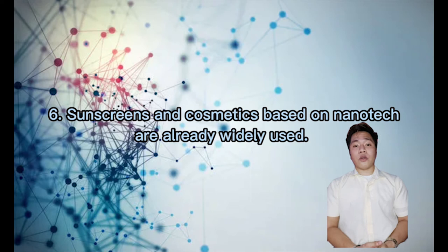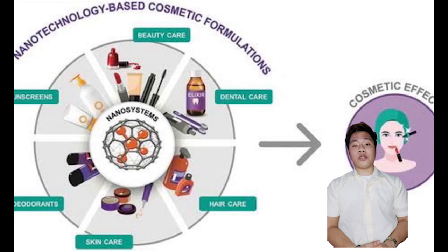Customers like products that are translucent because they suggest purity and cleanliness. And L'Oreal discovered that when lotions are ground down to 50 or 60 nanometers, they let light through. For sunscreens, mineral nanoparticles such as titanium dioxide offer several advantages. Titanium dioxide nanoparticles have a comparable UV protection property as the bulk material, but lose the cosmetically undesirable whitening as the particle size is decreased.